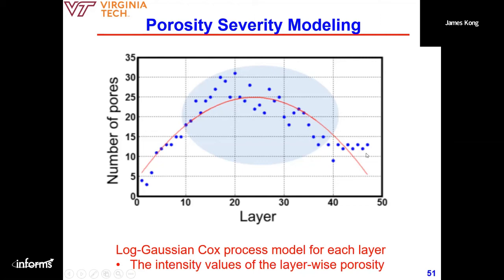So we can share this one with our domain experts, for example, my collaborators from mechanical engineering. They can think about what happened in the middle, right? What happened in the middle? This is also a very interesting example to show. In 3D printing, we should not just use one fixed set of printing parameters. Perhaps we need to change in the middle. This also shows that in 3D printing, our classical just one set of DOE may not work. At least several sets of DOE, right? But to simulate the printing in the middle layer is quite difficult, right? Then closed loop control is really necessary.